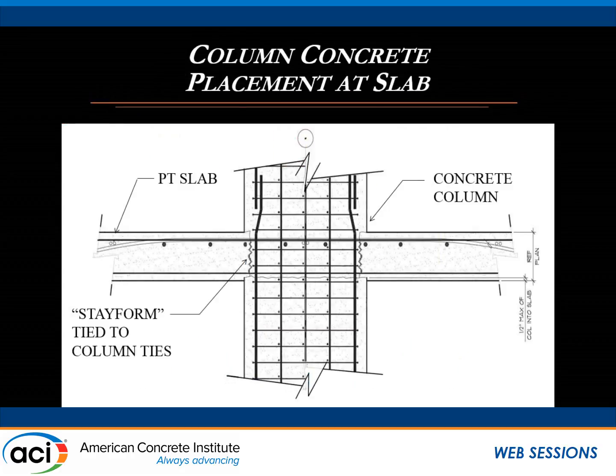When you have 15,000 PSI columns and 8,000 PSI slabs, that works very well when you have that sandwich of the slab right here. When it's confined on four sides, you don't have a problem. Then that sandwich will be about 14,000, and this is what we really needed for the strengths itself. However, some of these columns are on the edges, so they're not confined on four sides. That sandwich needs confinement, and you need a higher strength than the slab. We don't want to introduce puddling.